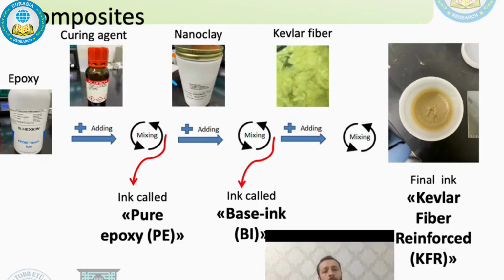This is the stage for ink preparation. First, we add curing agent to epoxy and mix it. In this stage, we call that ink pure epoxy. Pure epoxy ink has no rheology modifiers like nanoclay or reinforcements like Kevlar fibers. Then we add nanoclay to that ink and mix it. In this stage, we call that ink base ink. Base ink has nanoclay rheology modifier but no fibers. After that, we add Kevlar fibers to that ink and mix, and we get the final ink version, Kevlar